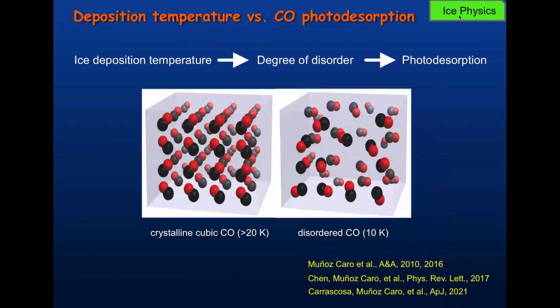Okay, so this photodesorption, we know it is dependent on the temperature that you use to grow the ice, whether you grow it at 10K or at 50K. You see the degree of disorder in the ice, so this would be crystalline CO ice, and this would be disordered or amorphous CO ice. This degree of disorder affects the efficiency of the photodesorption.